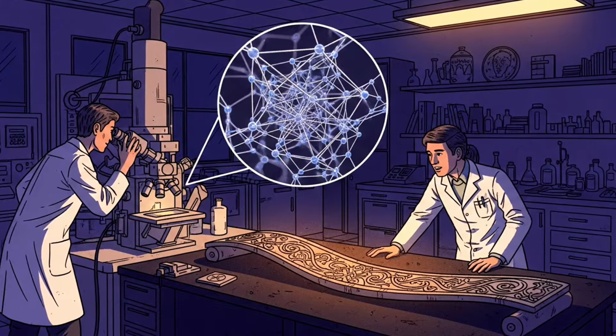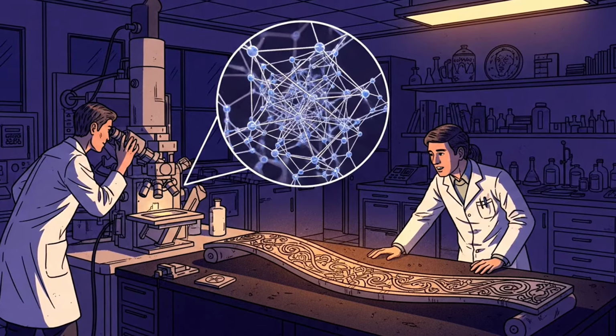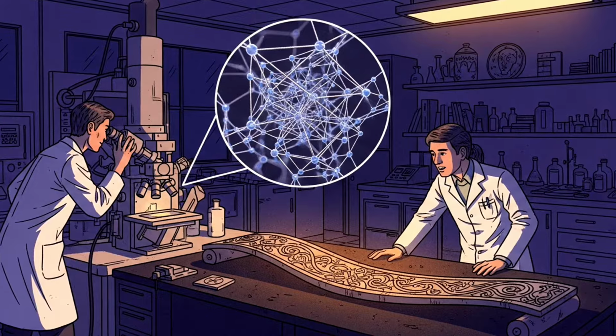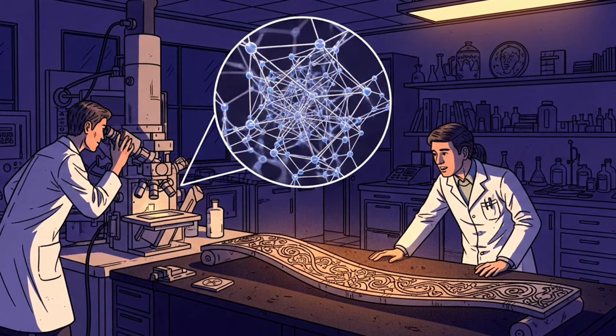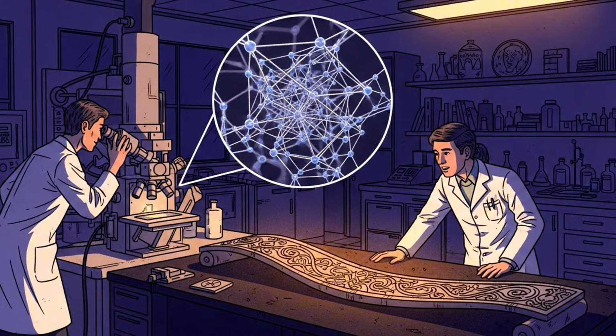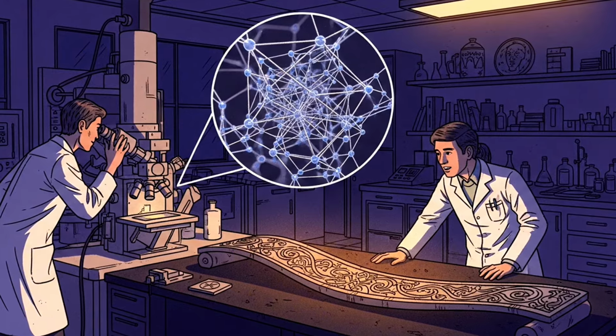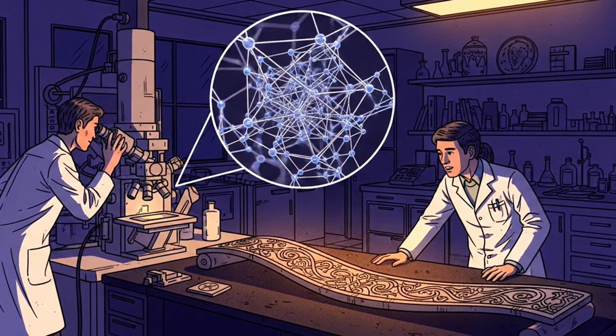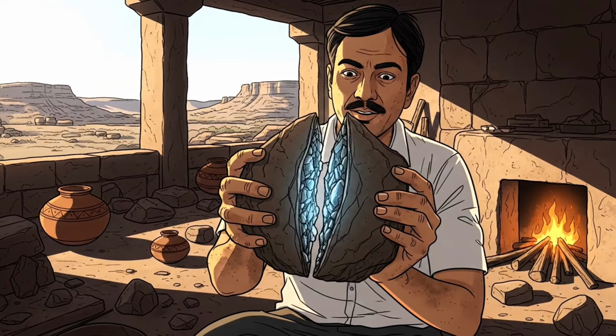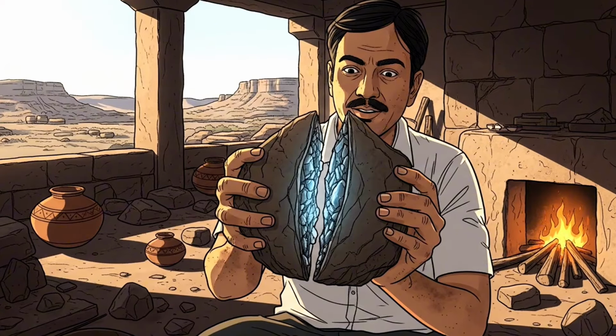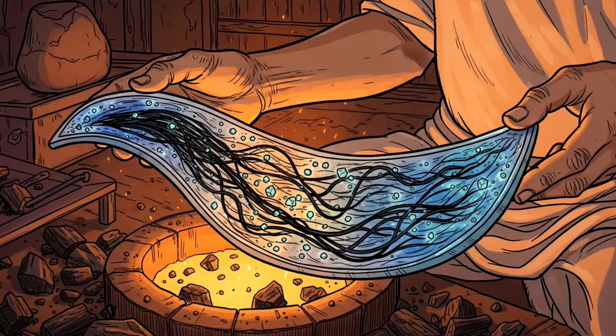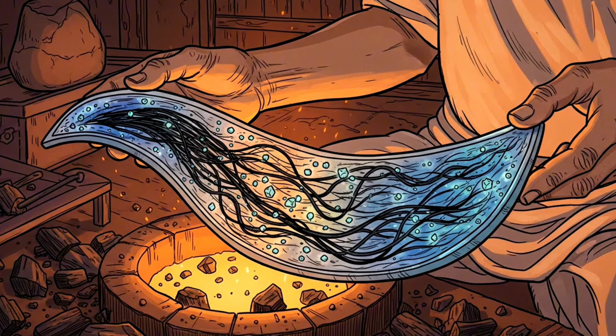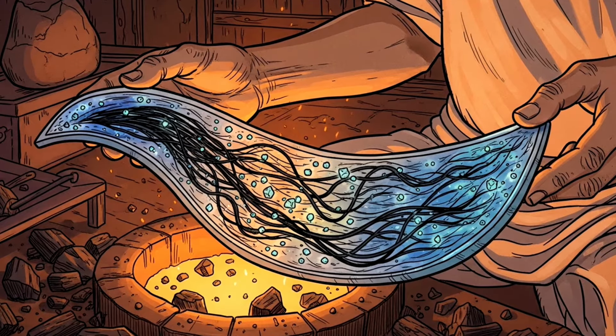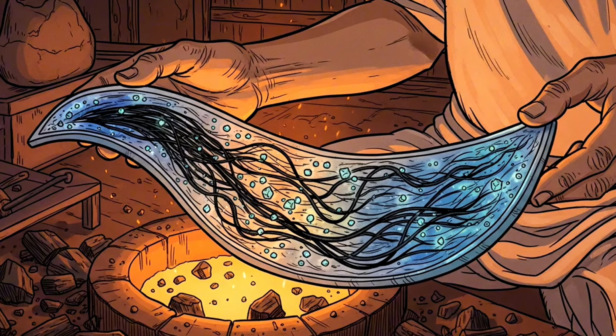When researchers John Verhoeven and Alfred Pendray examined surviving blades under electron microscopy, they discovered something startling. Carbon nanotubes and cementite nanowires distributed within the steel's microstructure. The critical secret ingredient was natural trace amounts of vanadium found specifically in Deccan Plateau iron ore. The vanadium seeded the growth of nanowire structures that gave the steel its extraordinary combination of hardness and flexibility.